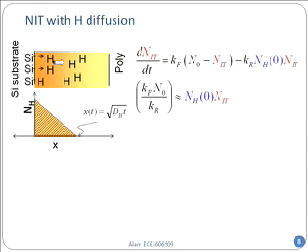Okay. Now, this is the crucial second step, and see whether you can understand it. There's a number of bonds that got broken, right? Hydrogen got away. Now, those will be diffusing, and you can see in the second plot, I have shown how far they will diffuse at a given time, square root of Dt. That's how far the hydrogen has gone, right? Okay. Now, the area under the curve is equal to the number of hydrogen which has been released.